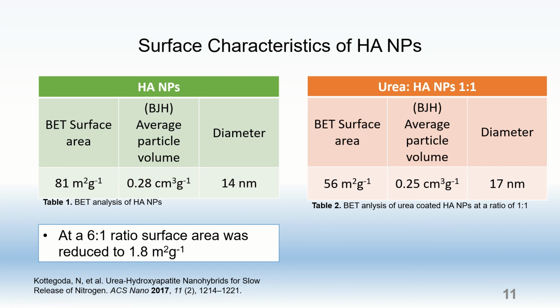it shows that the surface area decreases to 56 meters squared per gram, as well as the average particle volume to 0.25 centimeters cubed per gram, and the average diameter actually increased to 17 nanometers. The reduction in surface area indicates successful coating of urea to the nanoparticles, and this was further expressed once a 6-to-1 ratio of urea to hydroxyapatite was analyzed, where the surface area was calculated to be 1.8 meters squared per gram, thus confirming a greater coverage of urea on the hydroxyapatite nanoparticles, and this is in agreement with the TEM images shown previously.